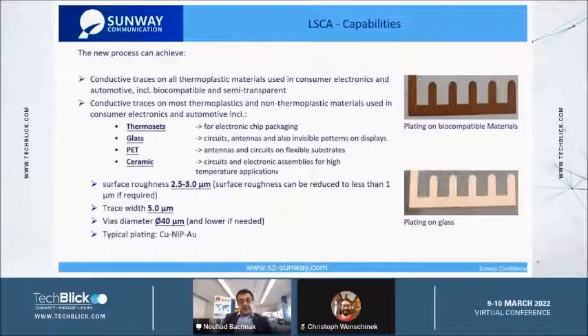Here are the capabilities I have mentioned already. We can do structure on nearly every material. I have presented here thermoset, glass, PET, and ceramics, some examples where we can use it. And additionally, the surface roughness is very low. This is good, for example, for antennas. And the width of the traces can go down to 5 micron.